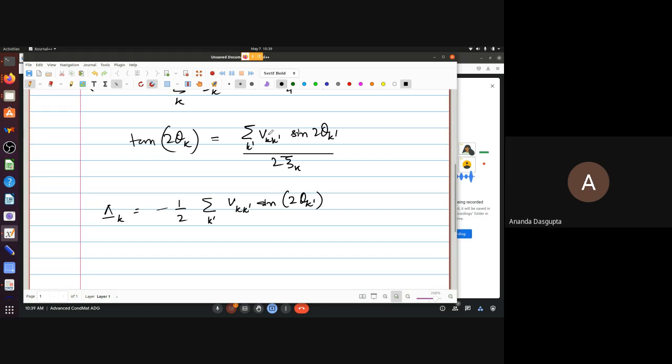And that will happen only because we have taken a very special Hamiltonian there. That's a result that we are going to derive soon. But we do expect the delta k to be a rather slowly varying function of k otherwise. So for many practical purposes, even when we are not working within the BCS model Hamiltonian, we might take delta k to be a constant.